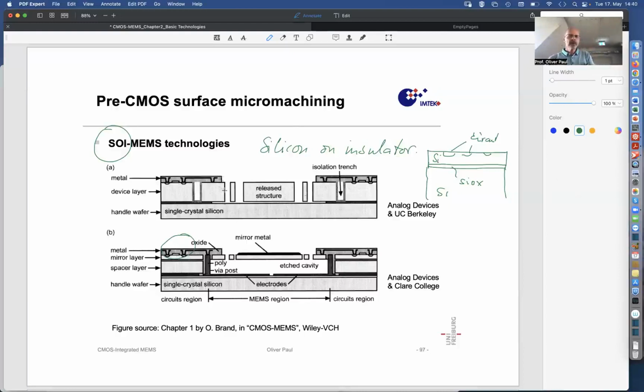So you can remove that layer of dielectrics here, and then you can etch into the silicon using, for instance, deep reactive ion etching, with vertical etch walls, as we've seen. And then you expose the buried silicon oxide, which can be removed using hydrofluoric acid or some fluorine-based vapor phase etchant, and then the silicon is released.